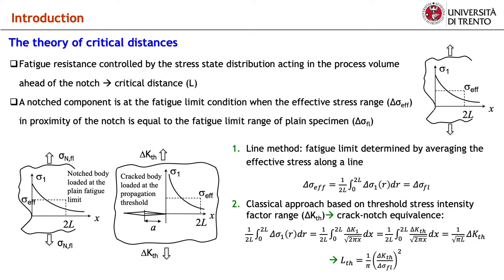The theory of critical distance encompasses several notch fatigue calculation methods that postulate the fact that a cracked or a notched member is in fatigue critical condition when the crack or notch stress field averaged over a control volume equals the plain fatigue strength of the material. In the classical formulation of the theory, the size of such control volume turns out to depend on the plain fatigue strength and the long crack threshold delta Kth.